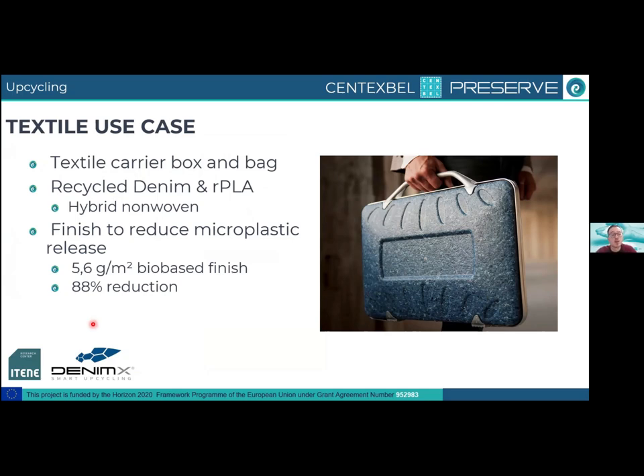Because especially with the non-wovens, you can see that there are fibers that can come out of this non-woven. So with this microplastic release finish, we can actually reduce these microplastics by up to 88%. Also, this is still at the end of the project. Still, we will make this and check this also together with the biodegradation to have a really good full overview of this.